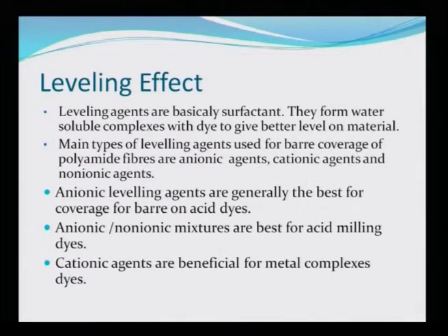Many types of leveling agents are used for barre coverage of the polyamide fibers: anionic agents, cationic agents and non-ionic agents. Anionic leveling agents are generally the best for barre coverage on acid dyes. Anionic and non-ionic mixtures are best for acid milling dyes, and cationic agents are beneficial for metal complex dyes.